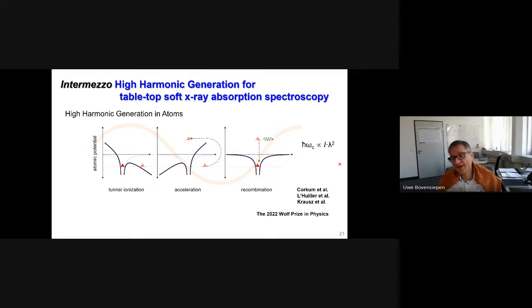And this harmonic emission that is here illustrated has a cutoff frequency, omega c, that is proportional to the intensity of the driving laser pulse, but also to the square of the wavelength. This might be a bit counterintuitive because it means that if you have a longer wavelength, so you go further into the infrared, you get a higher frequency in the emission.